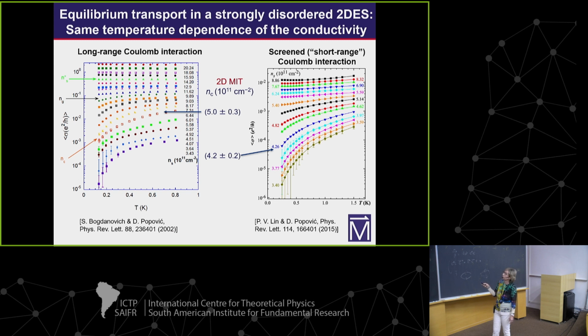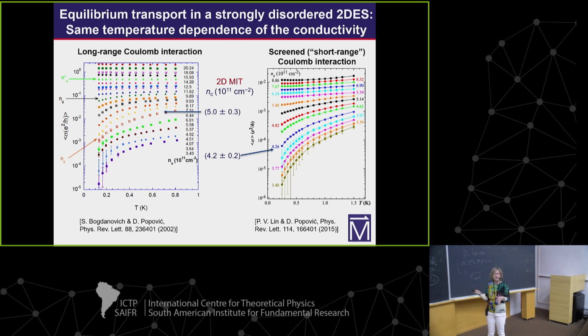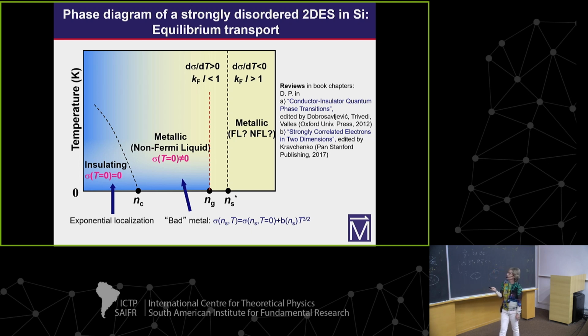So how do we know that we have a metal insulator transition here? I don't have time to show the data in detail, but basically we looked at the temperature dependence at all densities. At the lowest densities we found activated behavior, consistent with exponential strong localization. Above a certain density, that activated behavior vanishes—this is NC, the critical density for the metal insulator transition—and above that we saw a different kind of temperature dependence. This is summarized here.